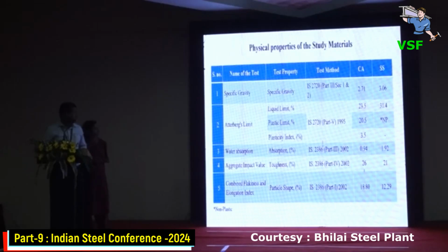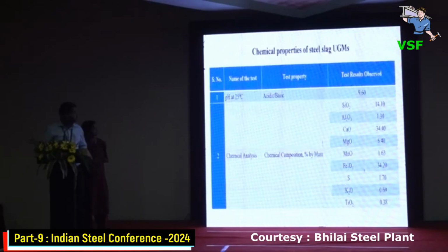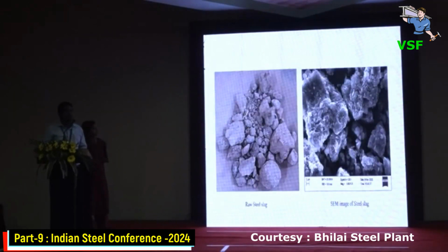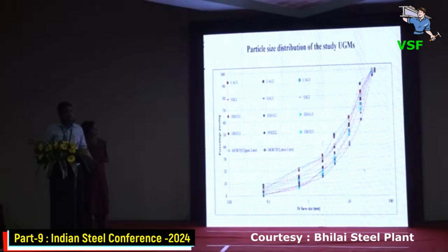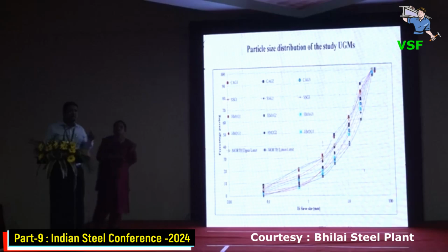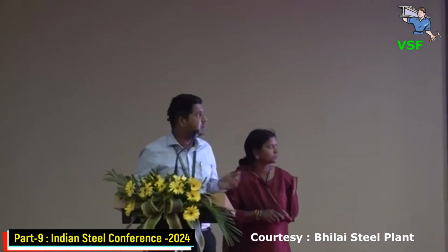These are the basic properties, these are the strength properties, these are the chemical properties, these are the raw steel slag images, and this is the microstructural property, the SEM image. This is the particle size distribution of the study material. We have collected steel slag from different depths that satisfy different ages, that is less than 1 year from the top layer, then beneath 5 meters we got 1 to 10 year old steel slag, and after 5 meters we get greater than 10 year old steel slag. So depending upon the age we have categorized the properties.